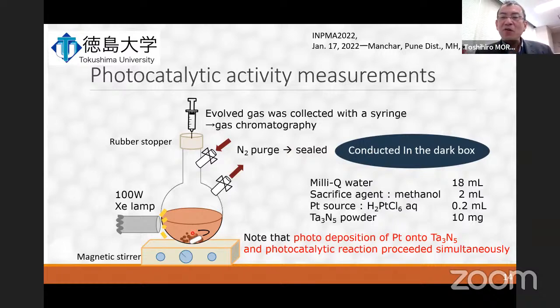Typically, 10 milligrams of the catalyst were loaded into the 200 milliliter Pyrex reactor here, with 18 milliliters of water, 2 milliliters of methanol as a sacrificial agent, and 0.2 milliliter of hexachloroplatinic acid aqueous solution added to the reactor. This is followed by purging with N2 gas under continuous stirring until all the air is removed.